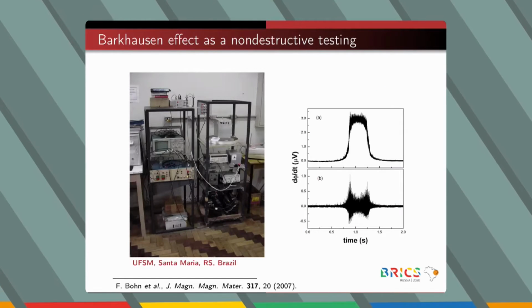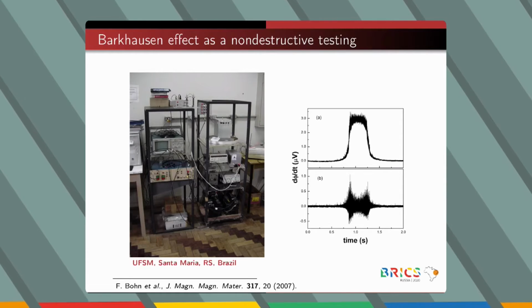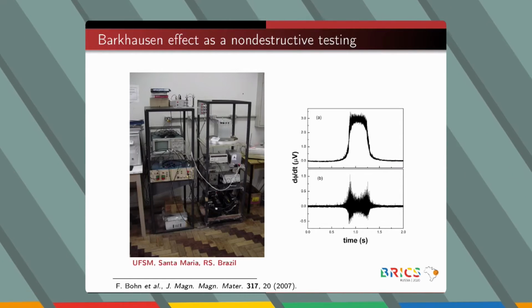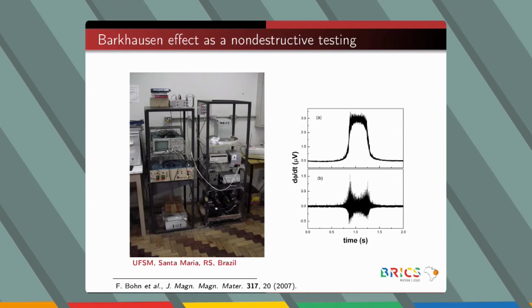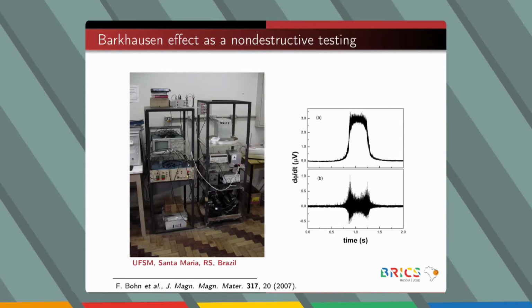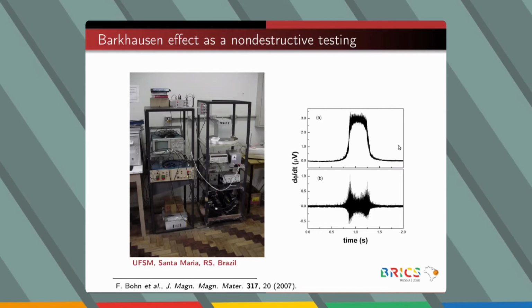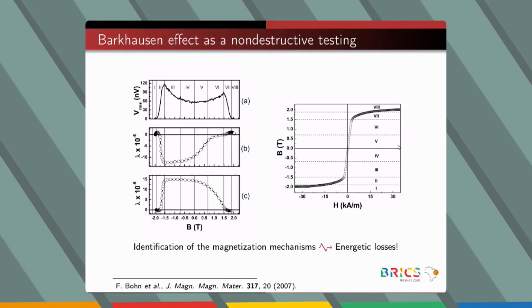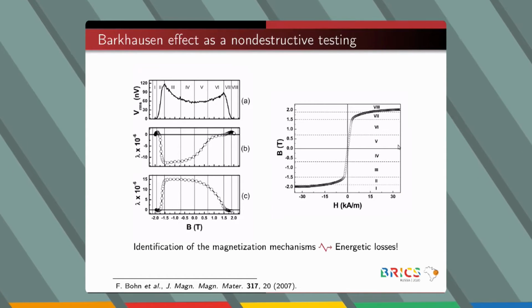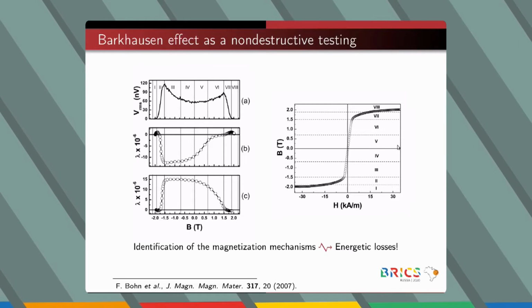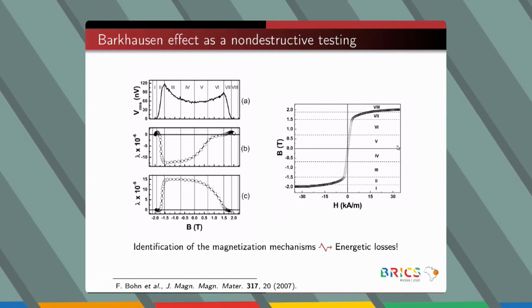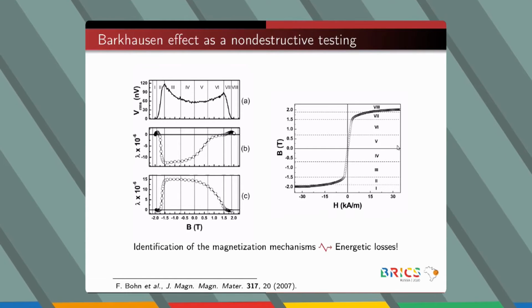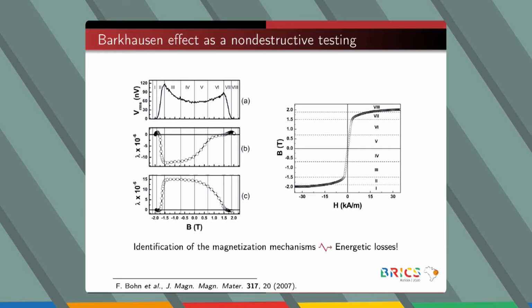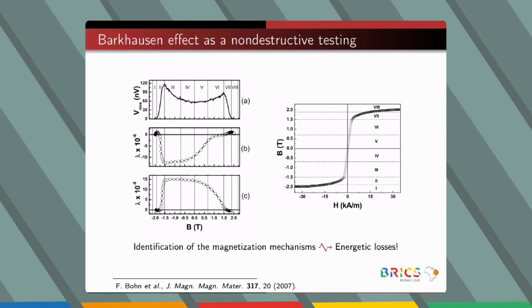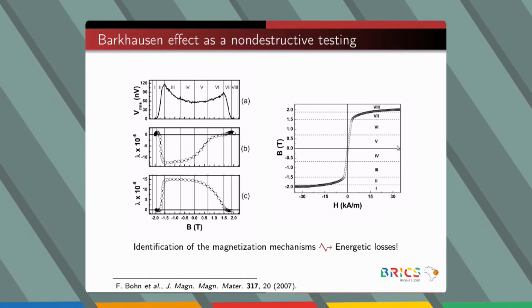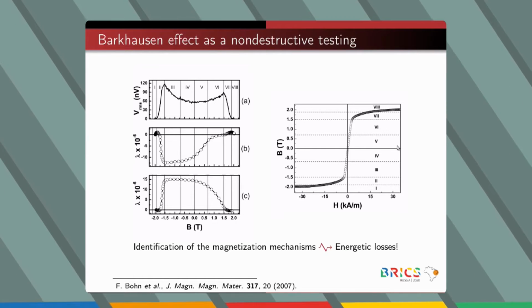Since the discovery of the effect, Barkhausen has been employed as a non-destructive testing to investigate ferromagnetic materials. From this perspective of materials science, for instance, we investigated this effect in non-oriented electrical steels. Then, combining Barkhausen effect and magnetostriction experiments, it was possible to split the magnetization curve into different regions according to the magnetization mechanisms, which are directly related to the energy losses in the material. This kind of study is very important because such materials are widely used in equipment such as engines and generators.